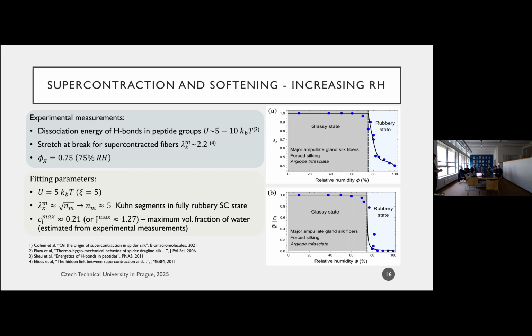In addition, if you stretch the fiber to failure, you could look at the maximum extension, and based off of that, you can estimate the number of freely jointed segments. So we've done that as well. The maximum volume fraction of water, that's also a quantity that we can estimate, right? So we had a lot of estimations here to see what these numbers that we plug in need to be. After we had this, we saw that this worked out pretty well. We compared it to other experimental findings, which I'm not showing here.